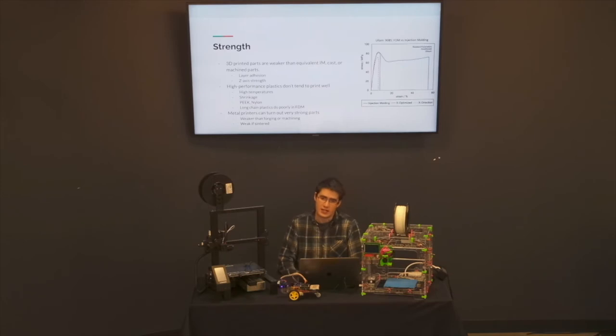Another reason is that long chain plastics really don't come out of a nozzle very well. If you have something like ultra high molecular weight polyethylene, that's a pretty low melting temperature. In fact, very friendly for a 3D printer. You'd think it'd be possible. But in practice, it clogs almost every time because the polymer chains are just too long. They get all tangled up and jam the nozzle. So these are some limitations that are not always present with injection molding because you don't really have to worry about tiny nozzles with injection molding as much.